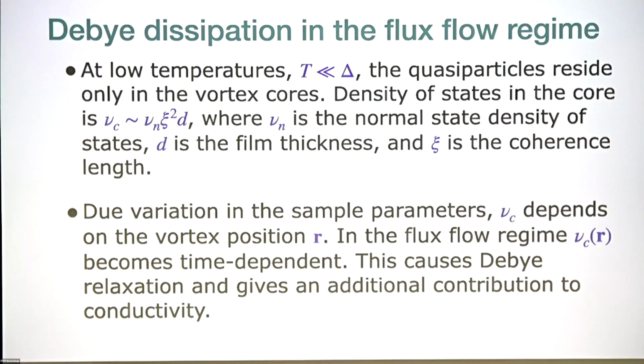But if your film is disordered, then the volume of the vortex core depends on the position of the vortex, because the film thickness may fluctuate from point to point, and also the coupling constant and diffusion coefficient can vary, and therefore the coherence length will also depend on position.